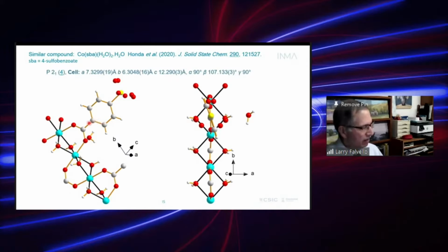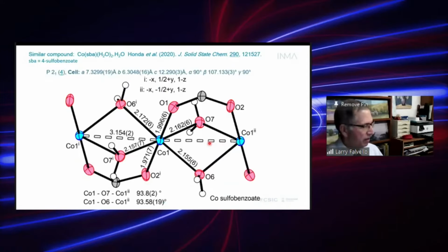Well, in this case, the crystals formed pretty well, it seems, to the extent that they made some single crystal magnetic susceptibility measurements. It's a different space group, but they have this similar arrangement of the cobalt polymer all in a plane, and the geometric parameters are very similar to the one that we characterized. The slight compression of the octahedra and short distance between cobalt atoms. And one other item, which they went to some